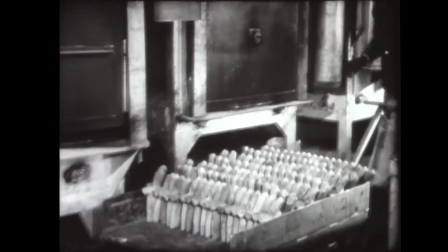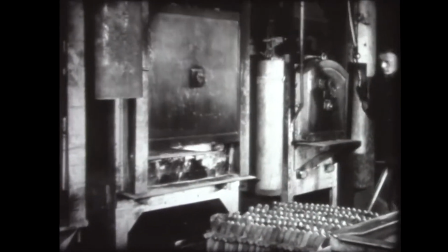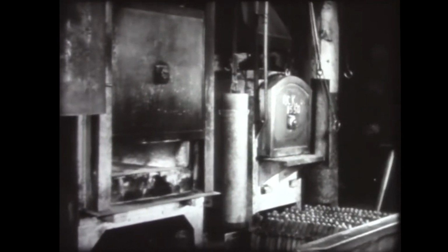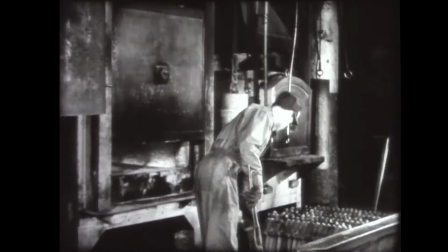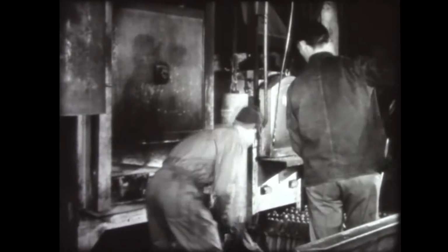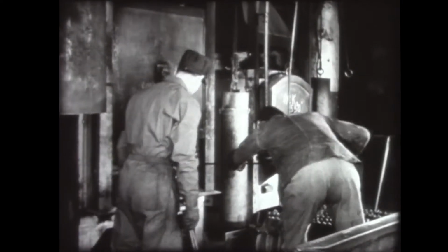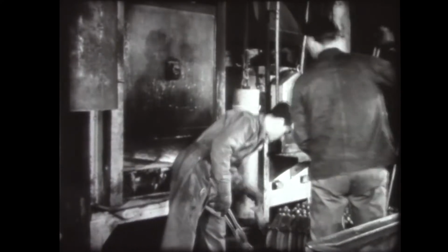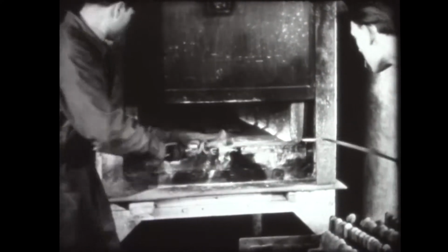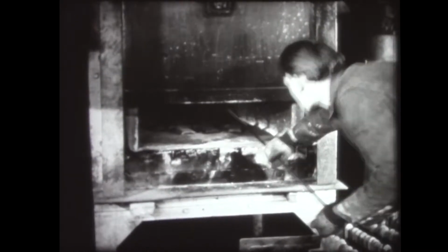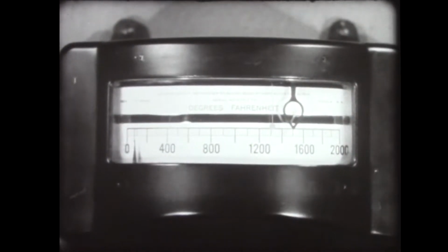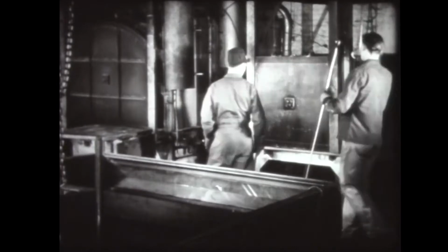These front guides are taken to the hardening furnace. Here begins the process which will bring about the desired final hardness and toughness. The guides are now the responsibility of the heat treater, who will see the job through. The furnace is charged with the parts and heated. On this instrument, called a pyrometer, the heat treater can read the temperature in the furnace. When the proper temperature is reached, 1500 degrees Fahrenheit in this case, the parts are removed from the furnace.